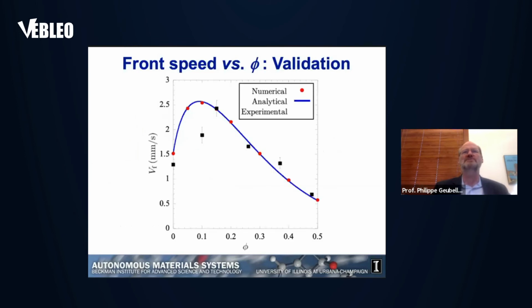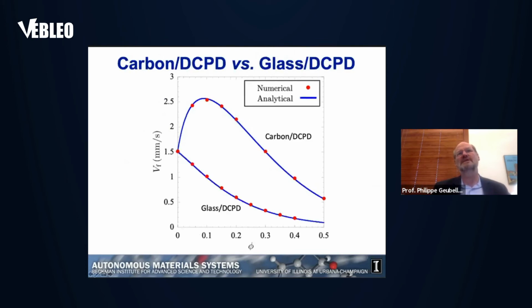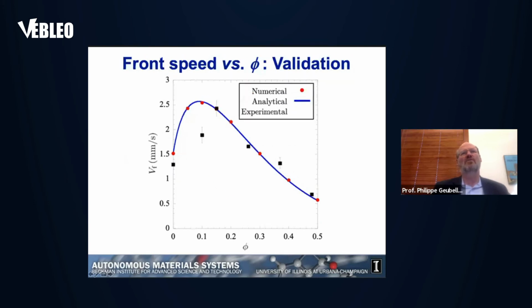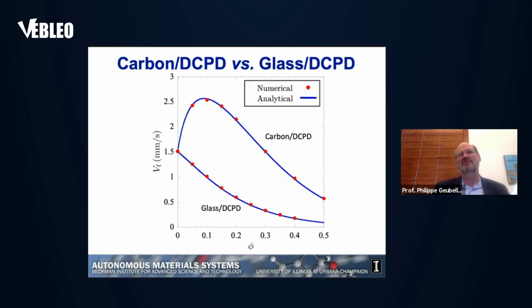So we actually compare this with some experiments. The match is not bad in the sense that we capture the fact that it actually increases and then starts to decrease as you increase the fiber volume fraction. And so we can also use this model to compare different types of reinforcement, whether you use carbon fibers or glass fibers. Glass fibers are less conductive than carbon fibers, so therefore we don't see this non-monotonic increase and then decrease of the speed of the front as a function of the fiber volume fraction, but we can see that it decays monotonically for the glass DCPD system.